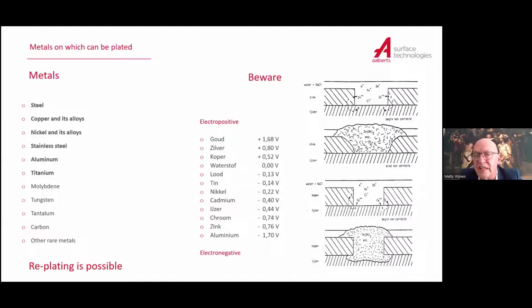This difference is in principle the same as a battery. That means that if you put copper in contact with iron, iron will dissolve and copper will be the cathodic element. So if I put copper on steel, as I've done on the below side, and there's a hole in the coating, a pore or something like that, and there's a solution there, then, due to the fact that iron will dissolve in preference to the copper, it will form iron oxide. You get rust on your part.